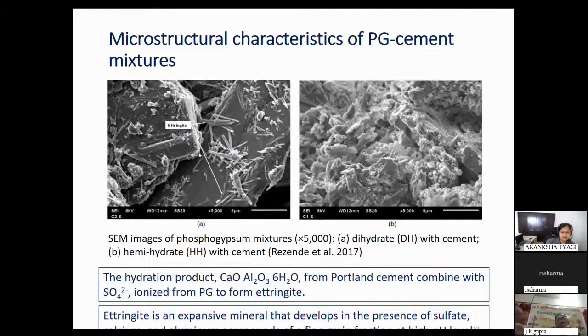So it is seen that when phosphogypsum is added to the cement or with this admixture, the hydration product CaO·Al2O3·6H2O from the Portland cement combines with the sulfate ion SO4 2-, which is ionized from the phosphogypsum, and it forms needle-like minerals called ettringite. So what this ettringite does is basically, it's an expansive mineral, and it develops in the presence of sulfate, calcium, and aluminium compounds. And it tends to fill the voids, the spaces. So at first, ettringite fills the void spaces and gives strength